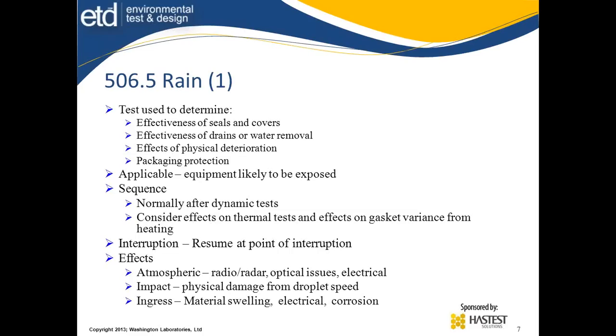Consider the effects of thermal tests and effects on gasket variance from heating. Sometimes a gasket overheated could cause a permanent set and not seal properly after it's cooled. So be aware of the expansion of metals that could have some ill effects there. Interruption is resume at the point of interruption. Almost always that's the case. If you do an overtest for some reason, obviously, and it passes, that's not a problem. If you failed and you've poured way too much water into it, you may have to consider restarting it from scratch to find out what really happens there.